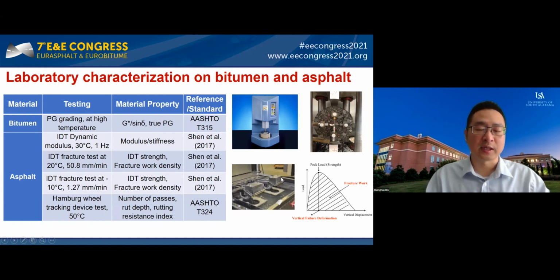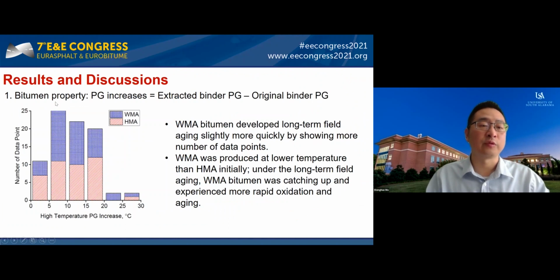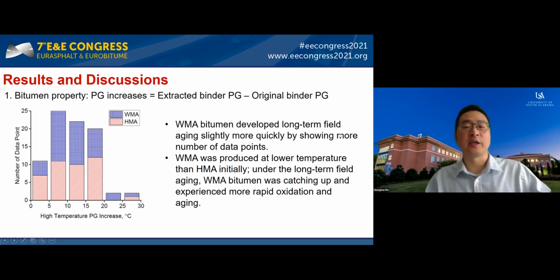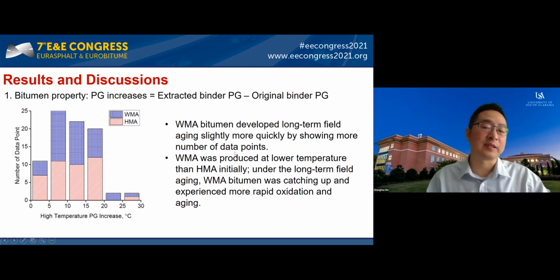So based on the field data, I want to present you the results and the findings in terms of the comparison between the WMA and HMA. The first one is about the bitumen properties. We are using the PG increase, which is calculated by the extracted binder PG minus the original binder PG. In this figure, you can see that the WMA is in blue and the HMA is in red. WMA bitumen developed long-term field aging slightly more quickly, by showing more data points. We also found that WMA was produced at a lower temperature than HMA initially. Under long-term field aging, WMA bitumen was catching up and experienced more rapid oxidation and aging.